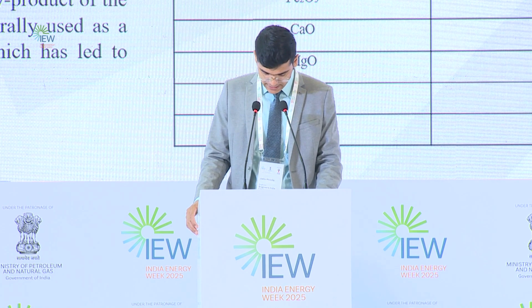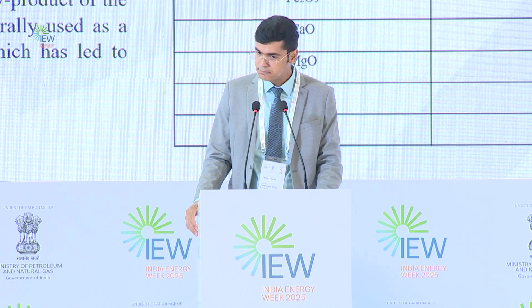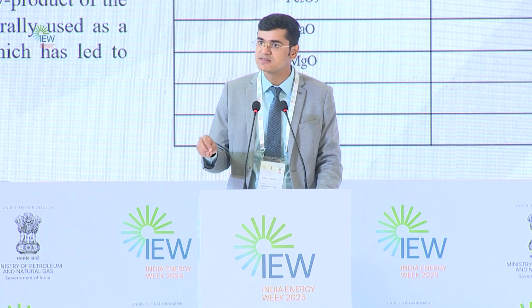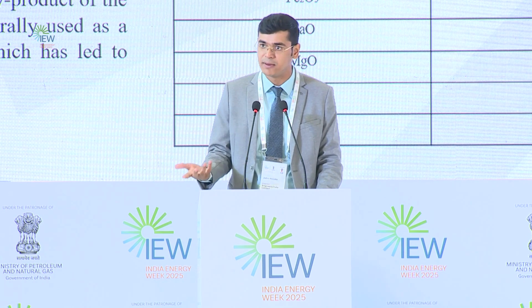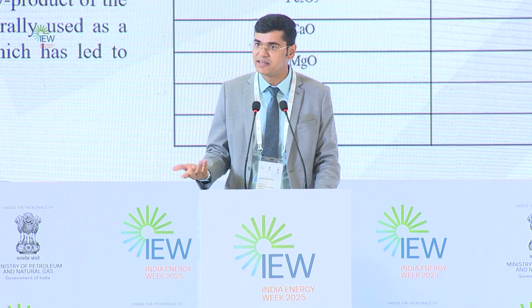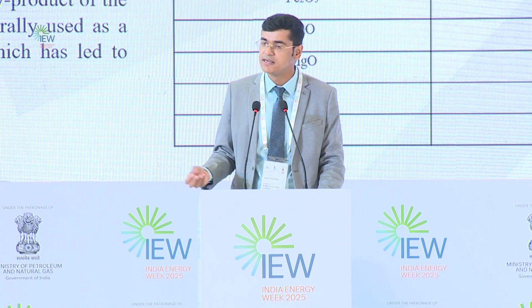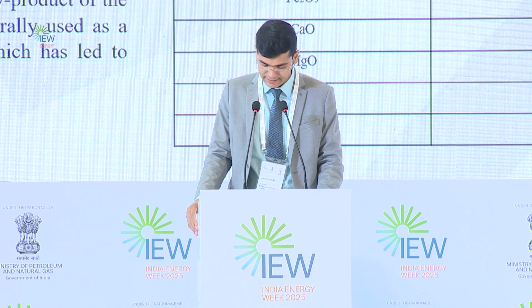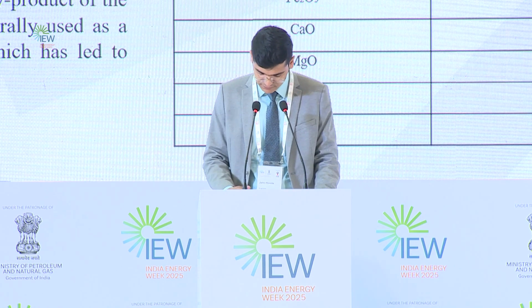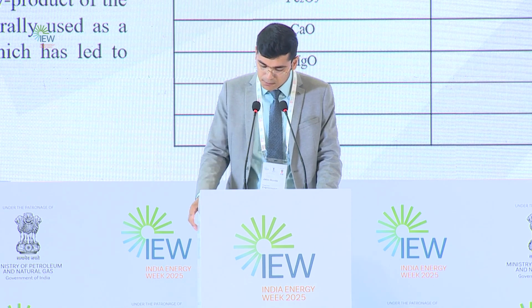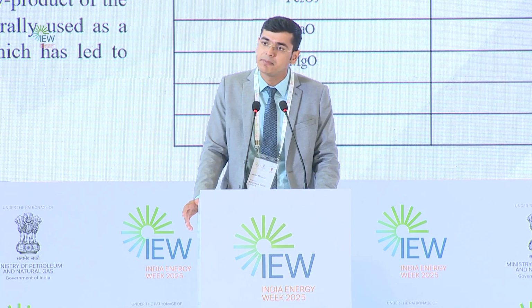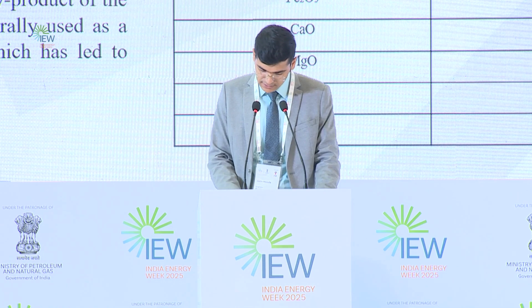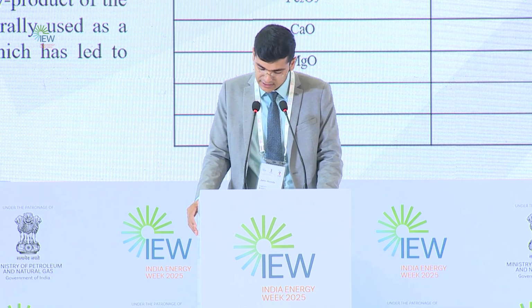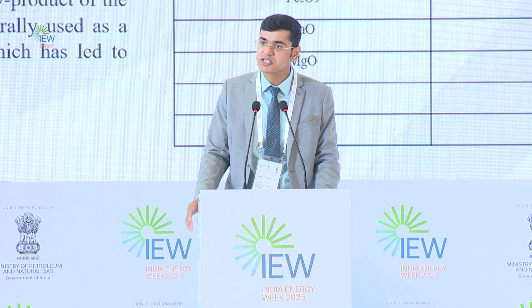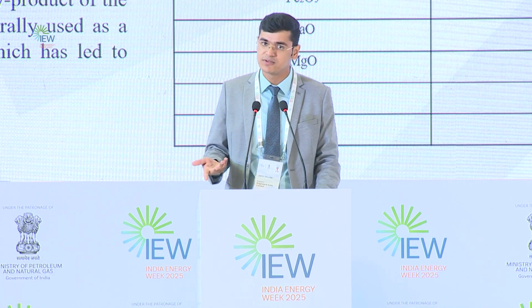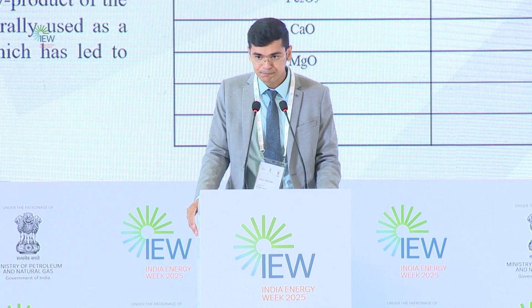ethanol blending plants, and it is often used as fertilizer, but when dumped onto grounds, it clogs the soil and may make the land barren. It is the general case in India that sugar crushers at roadsides dump such SCBA ash, which makes the land barren itself. It's of no use. So the SCBA composition you can see here is very much comparable to the cement composition. It has a silica content of 64%, alumina, iron and calcium. Such a composition is comparable to cement, and that's why we are using it as a replacement for cement.